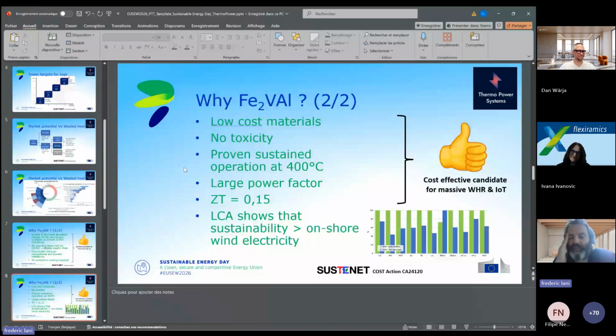So it can be operated up to 400 degrees C. It has a large power factor, actually very competitive. Its major drawback, I would say, is that the efficiency itself, often measured in terms of ZT for thermoelectric materials, is 0.15. So it's a low efficiency, which means we will have a low conversion efficiency.